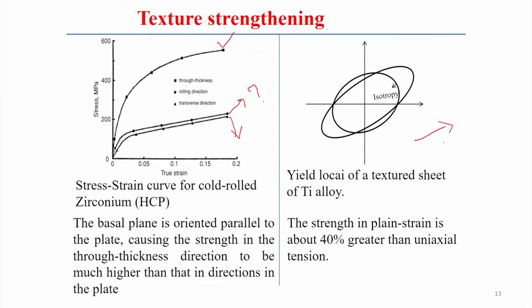Texture also affects the isotropic behavior of metal structures. The yield loci of a textured titanium alloy sheet show that the anisotropic behavior gives a plane-strain strength about 40 percent greater than uniaxial tension. The yield locus is larger than the isotropic case — that is because of the presence of texture.